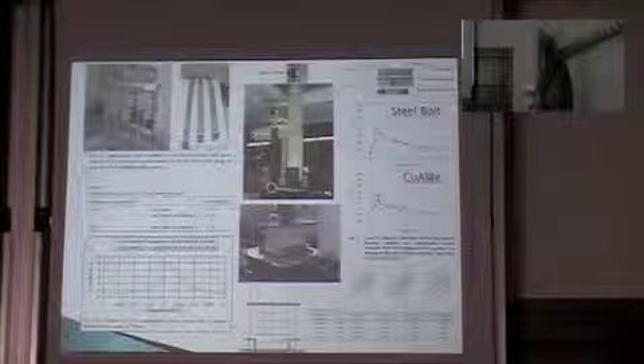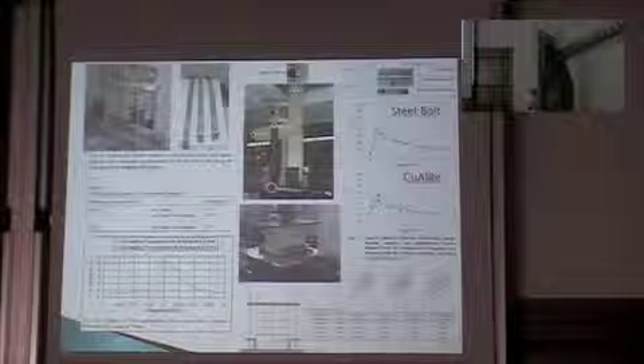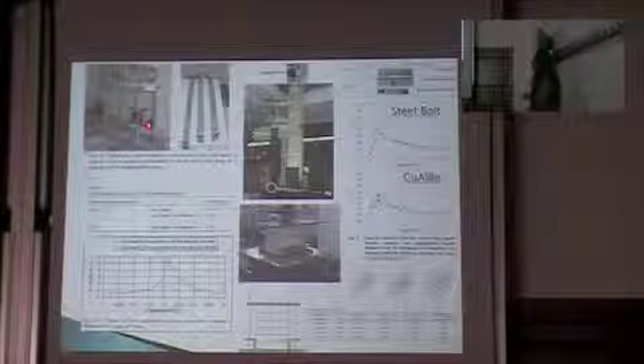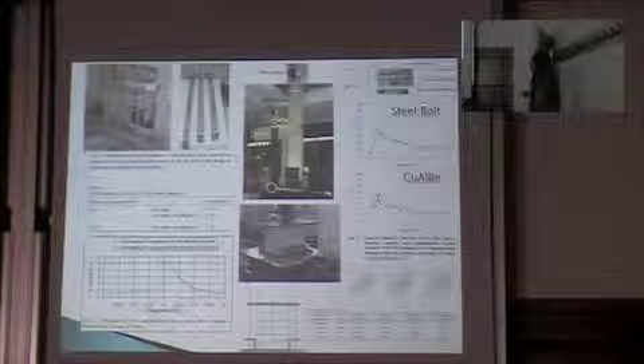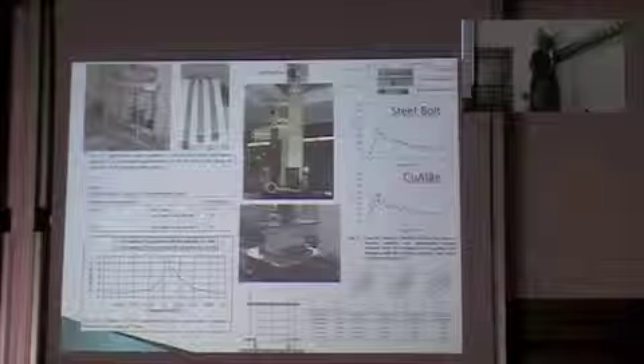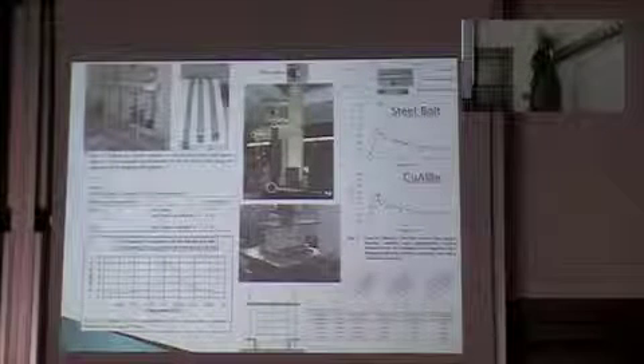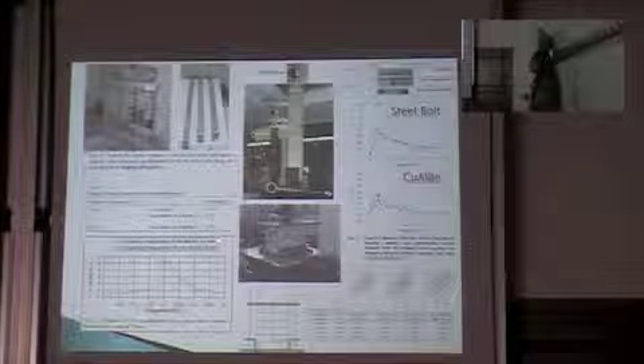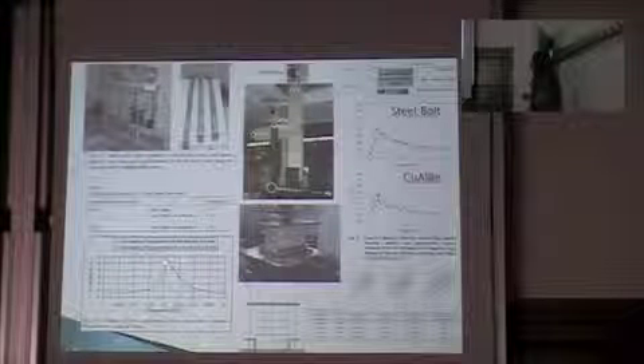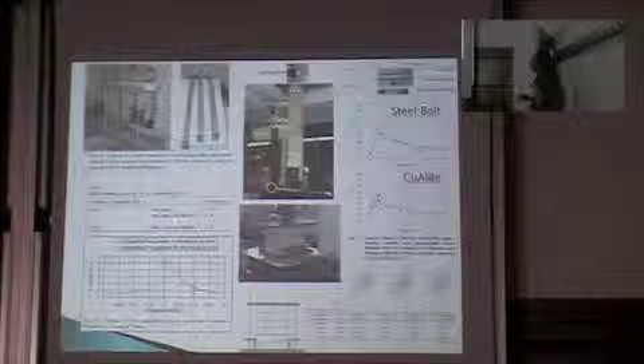Similar experiments were conducted by mounting the shape memory alloys in order to form some sort of composite material. So for example, here we combined it with the steel, and we made the columns of this single degree of freedom steel frame of composite shape memory alloy and steel. We can see how the frequency spectrum changes with the introduction of the shape memory alloy plates, but it doesn't make much sense to talk about frequency because the system becomes nonlinear. And so we try to characterize the nonlinearities of the system by conducting experiments of increasing amplitude and then decreasing amplitude. You see how the shift of the peak indicates that there are some nonlinearities affecting the dynamic behavior of the structure.